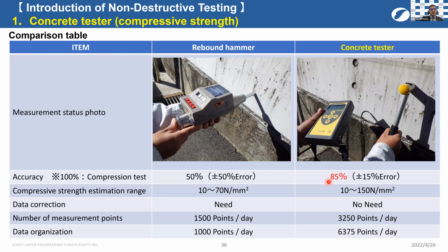So this is the numerical comparison between rebound hammer and concrete tester. The rebound hammer had an error of plus minus 50% in uniaxial compressive strength test result due to the unevenness of the concrete surface, whereas the concrete tester has improved accuracy of plus minus 15% error.